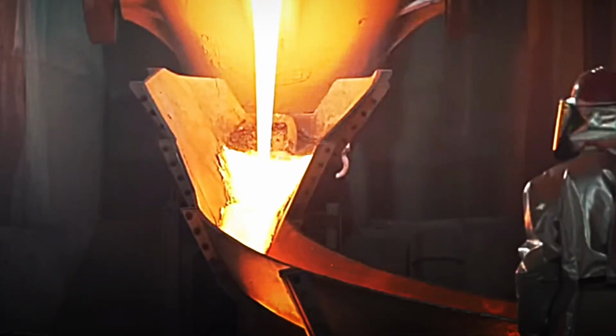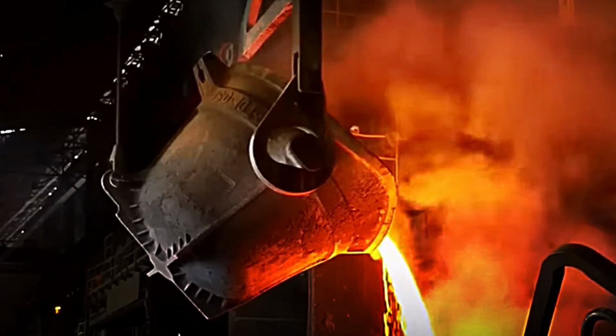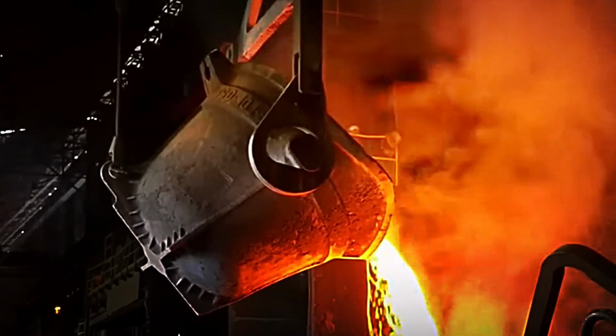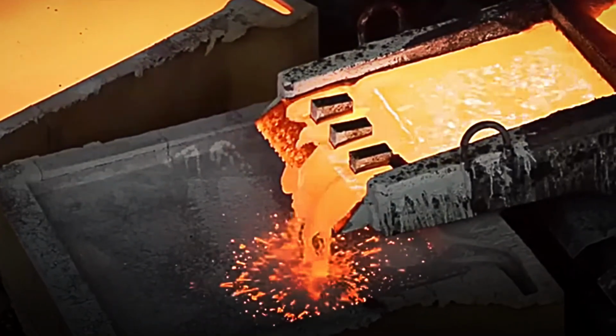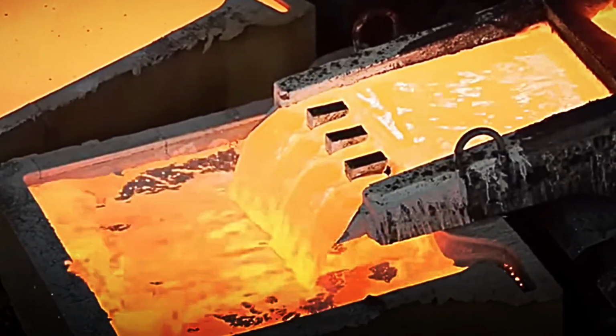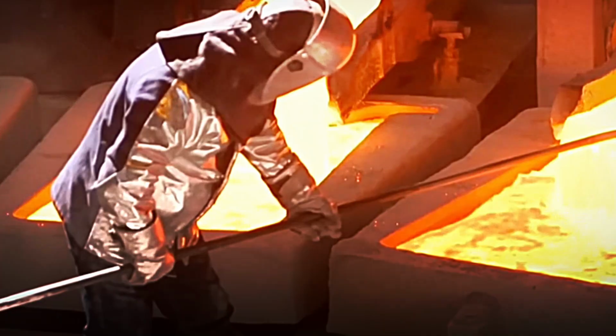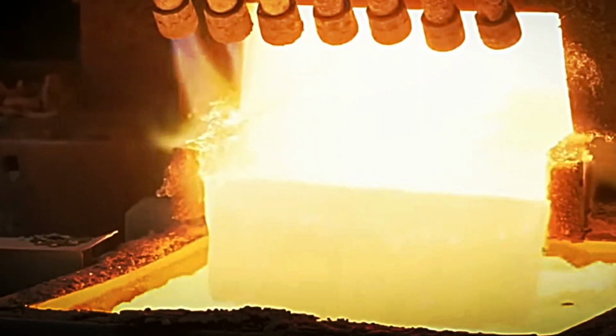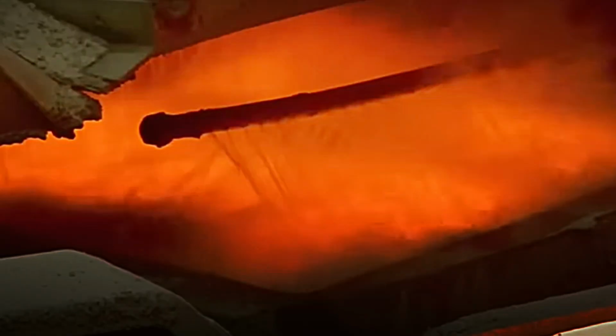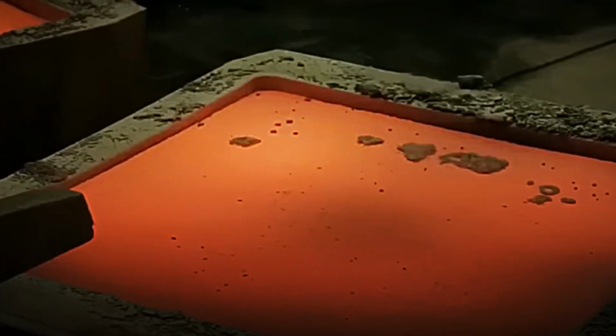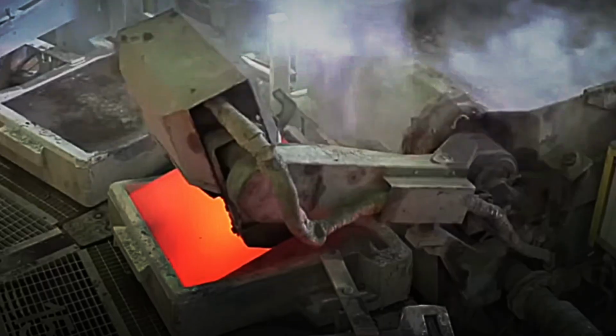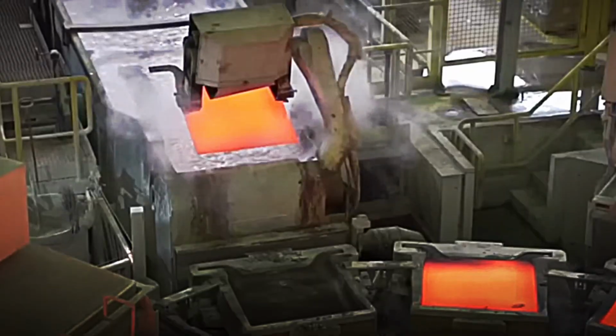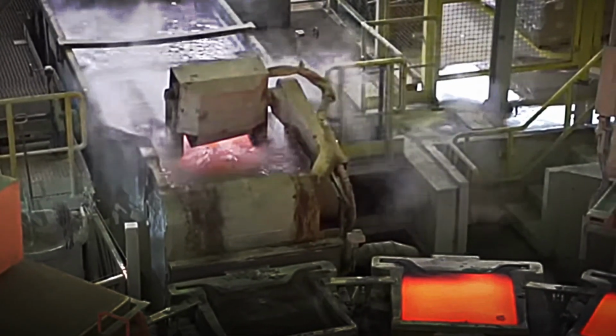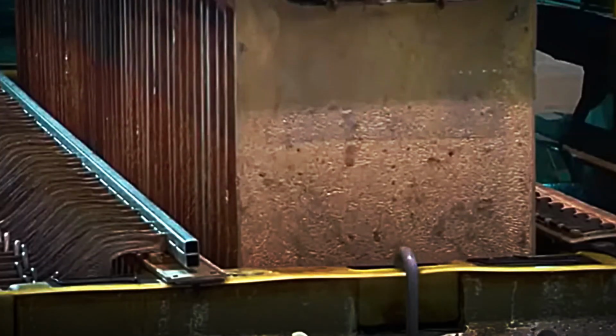At this stage, it is poured into molds forming large slabs known as anodes. The copper slabs, still with certain impurities, are transported to a refinery where the process is completed. There, they are placed in tanks with an electrolytic solution, facing thin metal plates called cathodes. When current is applied, the copper atoms migrate from the anodes to the cathodes, depositing as pure metal, while the impurities precipitate to the bottom. After several weeks, the result is 99.99% pure copper, ready to be transformed into cables, motors, and electronic devices.